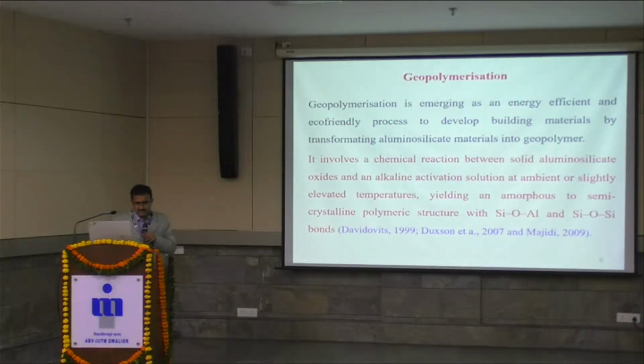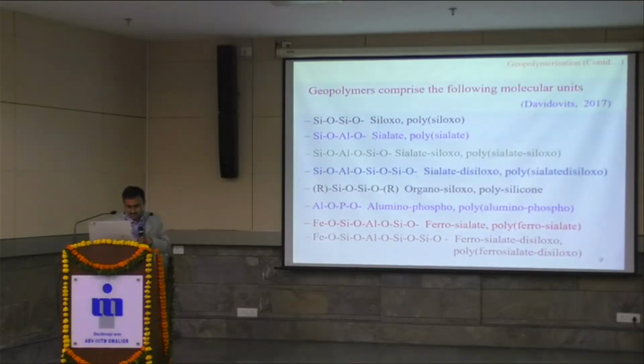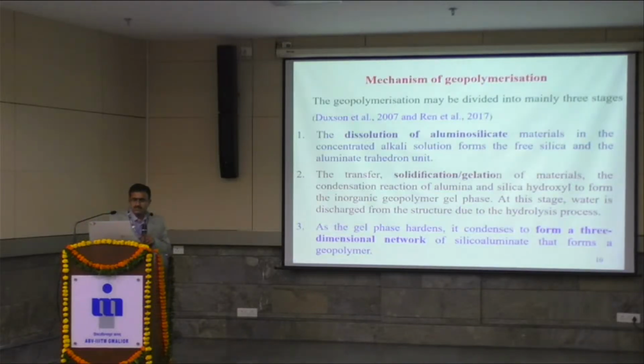The geopolymer, in fact, is a chemical reaction between the solid aluminum silicate oxides and alkaline activated solution at ambient or slightly elevated temperatures, yielding amorphous to semi-crystalline polymeric structures. It comprises several units: polysiloxo, polysialate, polysialate siloxo, and so on. This is the mechanism of geopolymerization. It involves dissolution, gelation, as well as hardening by formation of a 3D network.